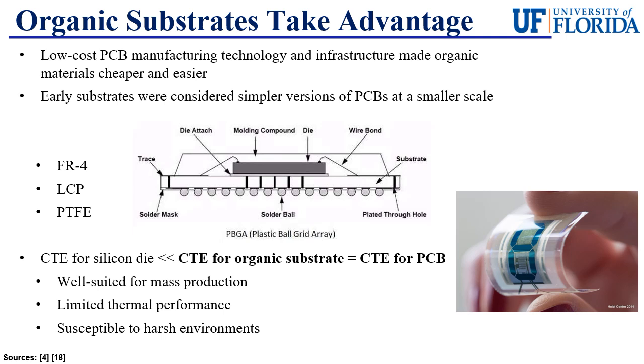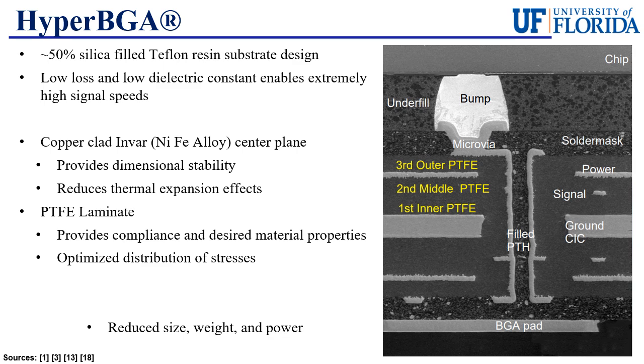Now, although organic substrates are well suited for mass production, they are limited by their thermal performance and susceptibility to harsh environments and high processing temperatures. The Hyper-BGA is an example of an engineered organic substrate using a Teflon-based composite with silica filler. The use of Teflon provides a low dielectric constant that leads to low loss, enabling extremely high signal speeds but requiring more passivation. And the silica filler is implemented to decrease the coefficient of thermal expansion of the organic Teflon to be in between that of the silicon die and PCB.